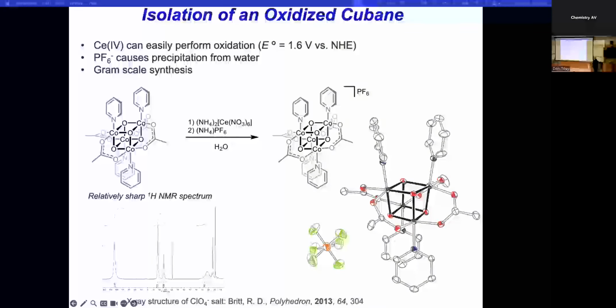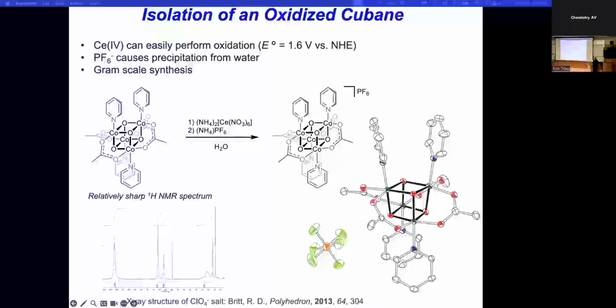Okay, so one of the first things Andy was able to do is show that he could oxidize the cube in a one-electron oxidation with cerium. So that gave us a crystal structure of this oxidized species, which again, formally has cobalt-4 in it. You can think about it as formally cobalt-3-3-3-4. The question of where the hole is still something we need to address.